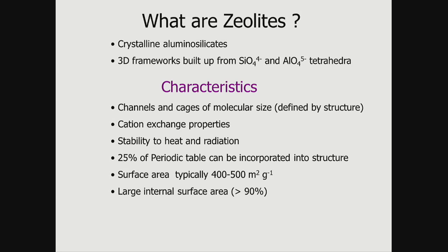Well, if you look at the structure, each tetrahedra atom has the spokes coming out, which are oxygens, going to the next atom. But then it goes to another one, and another one, and another one, and they're all interconnected with very little loose edges. When you do that, it means that each bond has half an oxygen. Not a whole oxygen, it's got a half oxygen. So it means that it's SiO2, so you should be writing that down, versus AlO2. AlO2 is negatively charged, SiO2 is neutral. So consequently, the aluminium gives you the charge.